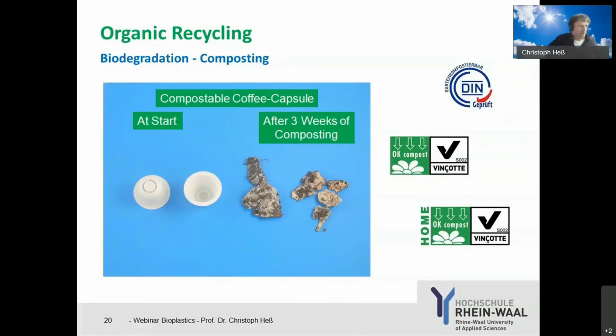On this slide we see an example for a compostable product, a coffee capsule. You can see here to the left this compostable coffee capsule. At start it looks like this, and after 3 weeks of composting we can see already a fragmentation. There's some contamination with soil, with compost, but the coffee capsule falls apart in smaller particles, and after another, let's say, 8 or 10 weeks, it will have completely disappeared and biodegraded.